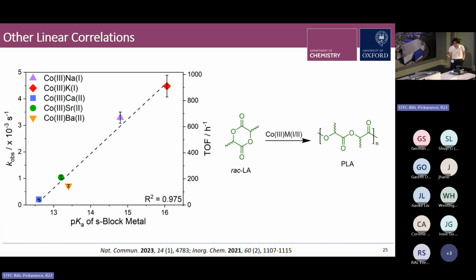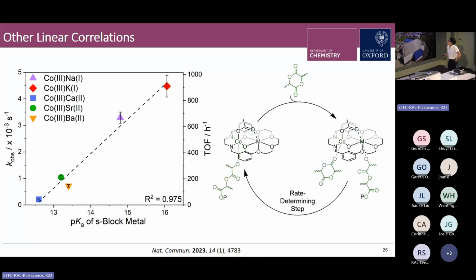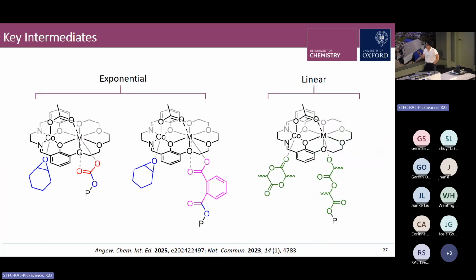And here we tentatively rationalize the linear correlation with respect to the proposed catalytic mechanism and the key rate determining intermediate, which involves ring opening of a cobalt-bound lactide by this S-block metal alkoxide nucleophile. And we hypothesize that the linear activity-acidity correlation relates to the alkoxide nature of the key rate determining intermediate. But just to reiterate, in the cases where we have a carbonate or carboxylate key rate determining intermediate, we propose that links to nonlinear activity-acidity correlations.